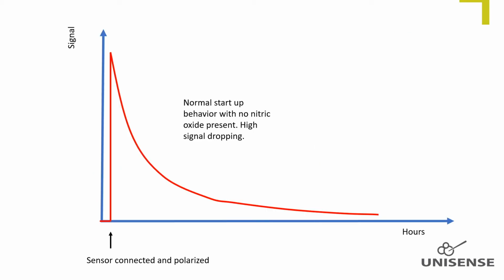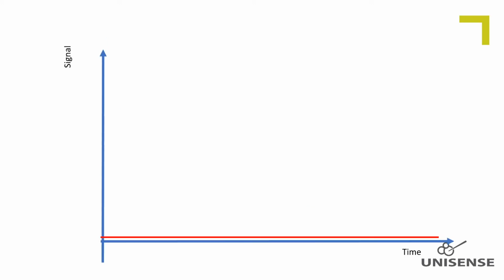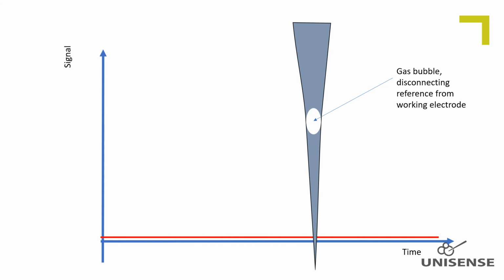These curves illustrate a normal startup behavior of a nitric oxide microsensor when connected to a Unisense amplifier and polarized. The signal is high and downward drifting right after polarization due to unspecific reaction on the working electrode. If there is not such an initial peak signal, but instead the signal does not rise much from zero, it might be due to a gas bubble stuck in the tip and which disconnects the working electrode from the reference.